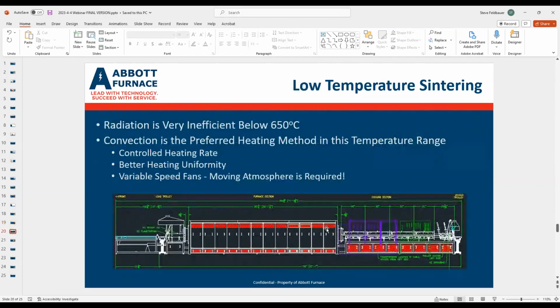Okay. However, the low temperature is a different design, and it's because in this temperature range, to be able to control your heating rate, and as you know, aluminum has a much lower melting temperature, right? So you're going to be well below 700 degrees C. In this case, you lose your radiation from the elements, right? The elements are running at a lower temperature, and to be able to control this heating and to be effective, you need to have convective heating. And so this type of system actually has a convective heating component to be able to control the heat up and control the temperature uniformity,